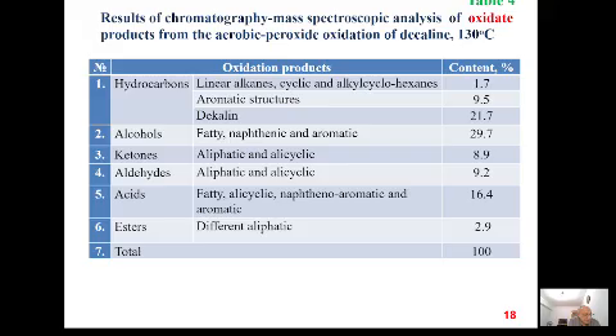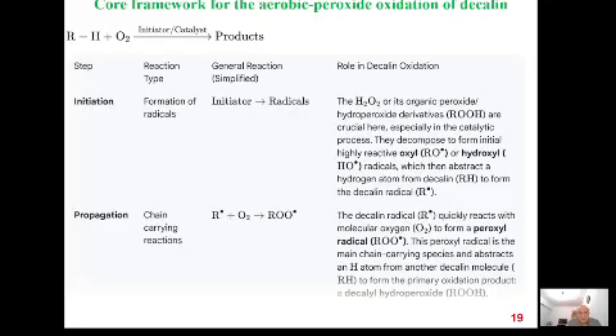It has been concluded from the GC-MS spectrum that the chain reaction of oxidation of decalin proceeds with destruction of the framework of the naphthenic cycles and with concomitant processes of oxidative dehydrogenation, functionalization, and alkylation of intermediate molecular fragments. The general scheme and proposed mechanism of the catalytic stage for the aerobic peroxide oxidation of decalin in the presence of ferrum-containing multi-walled carbon nanotubes are depicted in slide number 19.